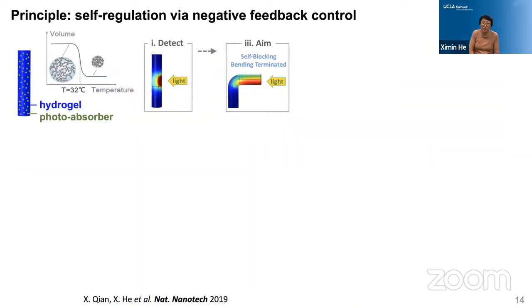So here I will reveal the secret behind. So here we didn't really invent the material chemically. We still use this very well-studied thermal-responsive hydrogel NiPAM, and we incorporate photoabsorbers in it. And it can be gold nanoparticles, can be reduced graphene oxide, or even carbon black. So when you shine the light, this photothermal gel will shrink, and if you balance the light intensity and the photo absorption and the shrinkage of this gel, it will create this local heating and create this bending motion.